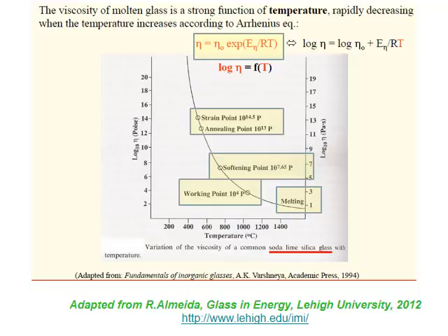At this temperature, the glass is still too hard to deform, but is soft enough for the stress to relax. We have already commented on the need of annealing in order to release stress. This stress release occurs in some minutes if annealing is performed at Tg, and in some hours if performed at the strain point.